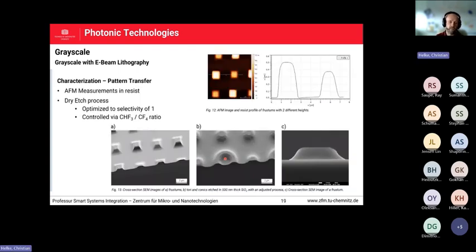Here again, some nice images of structures we realized in some experiments so far. And again, here are the pyramids, for example, with 500 nanometer height, and here something about 400 nanometer height. This is everything after etching in 500 nanometer silicon dioxide layers so far. Here we have the donuts and the circle structures, and here again a cross view of the pyramid structures.